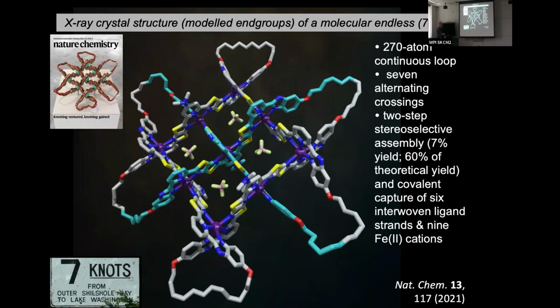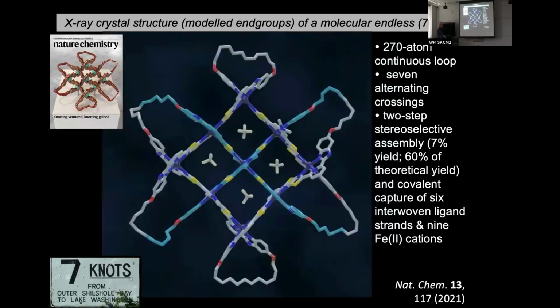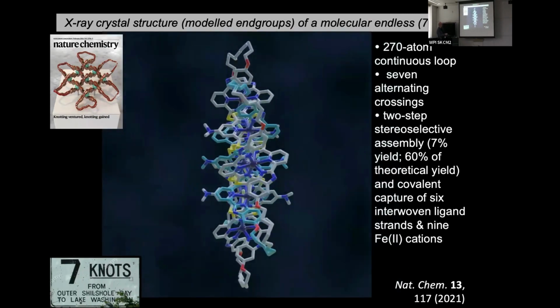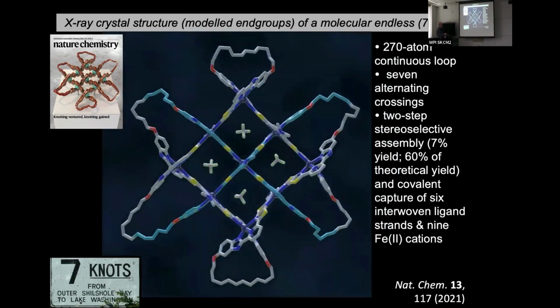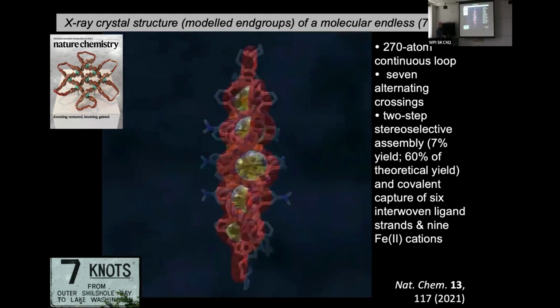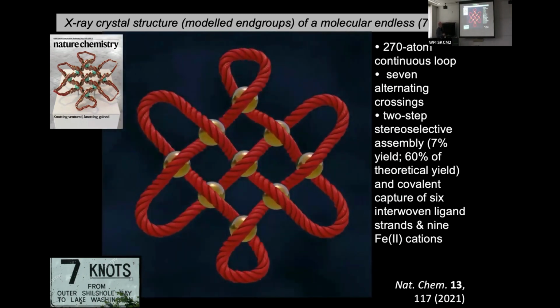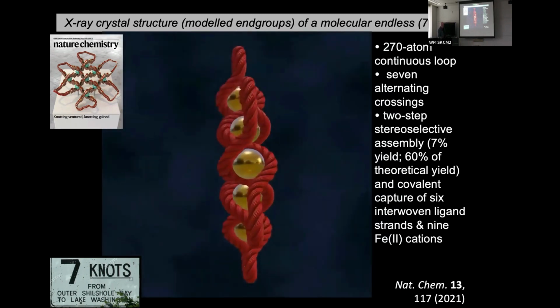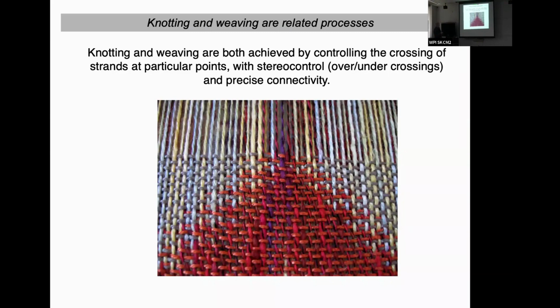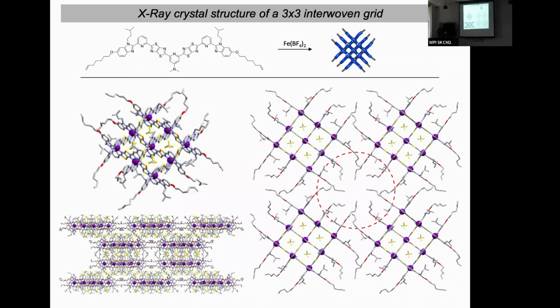We can use it in the construction of other molecules. And if we rotate around here, we can see that it's a completely flat structure with the metal ions in the center of these 3x3 grids, and it has the same topology as a Chinese knot with the nugatory crossings at the end. So knotting, of course, is related to weaving. They're both achieved by controlling the crossing of strands at particular points, and you need to control the stereo control of those crossings, whether they're over or under, and control the connectivity in order to form a continuous woven structure rather than a mess.